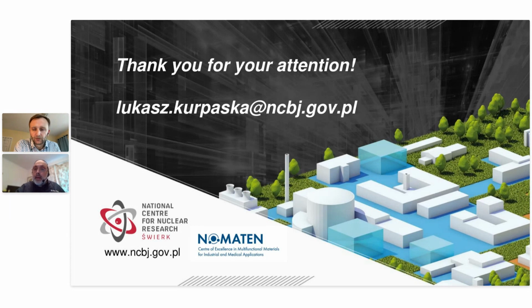Okay, and then a question from Taylor. Do you expect annealing away of irradiation defects when nano-indenting at elevated temperatures and above irradiated temperatures? That's a very good question. This is our next step. For the moment, the high temperature measurements were done only on non-irradiated specimens, and of course we expect annealing of defects at high temperature when you heat up the system.